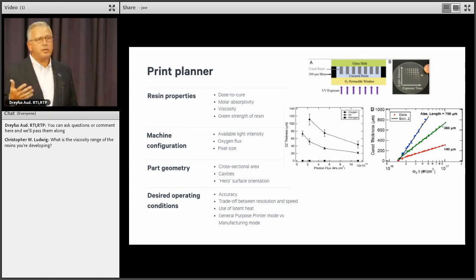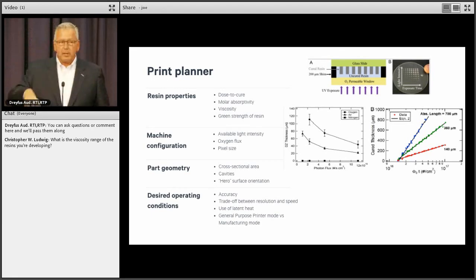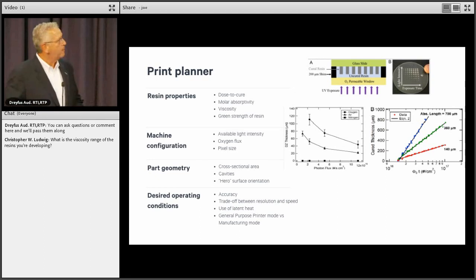And so every time we change the resin, the details of the resin matter: the reactivity of the resin, the dose to cure, the viscosity of the resin, how far the light penetrates, the molar absorptivity, and the green strength of the part, because we're actually physically pulling the part up and there are a lot of forces on the part. We do finite element analysis on that part as we pull resin in underneath. There are details of the machine configuration. What is the light intensity and how do we control the light intensity? How much oxygen are we letting through the window, and controlling that by controlling concentrations and materials? What is the pixel size?